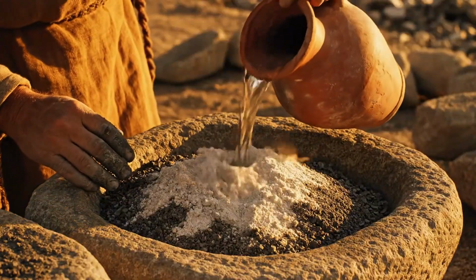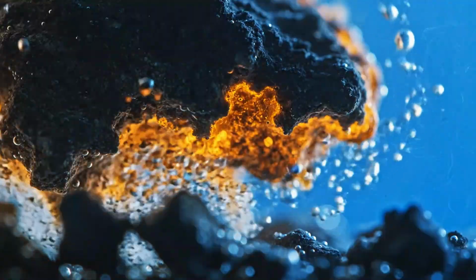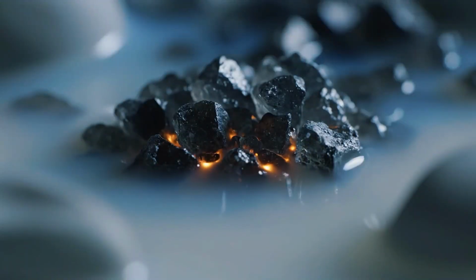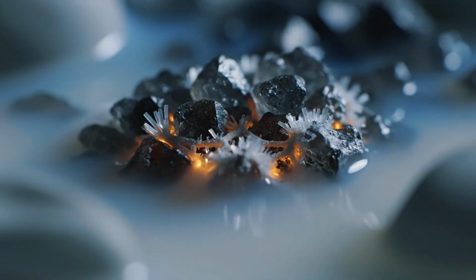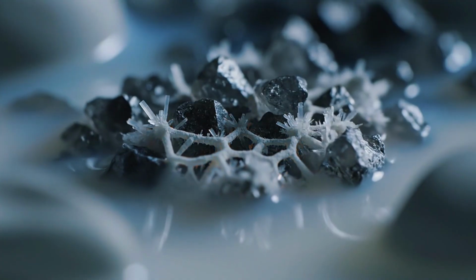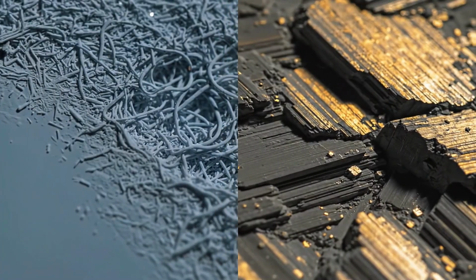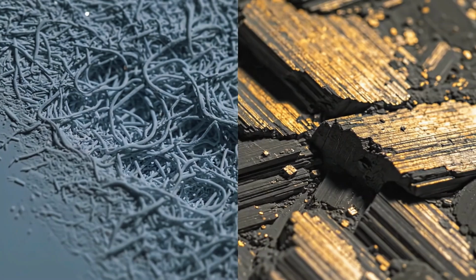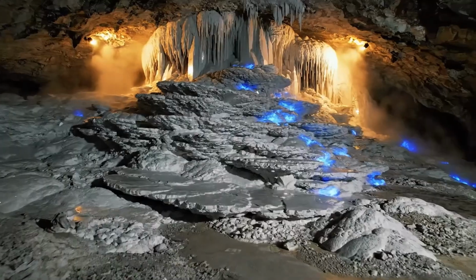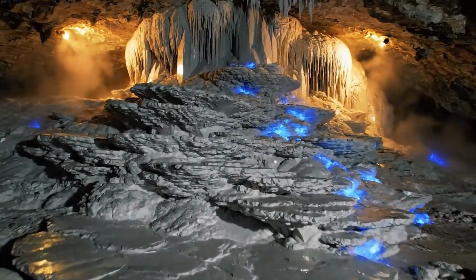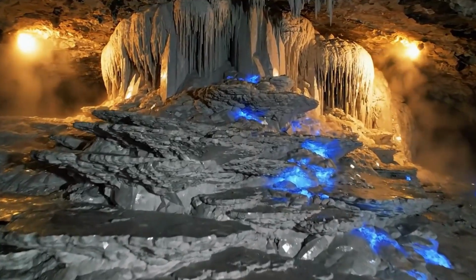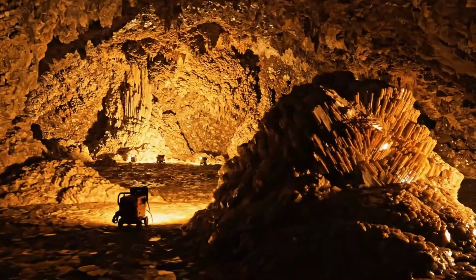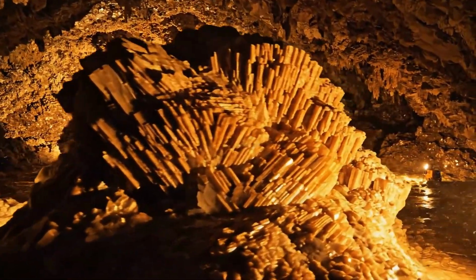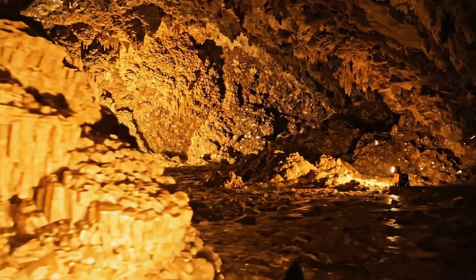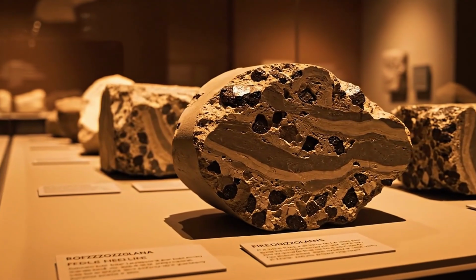When the lime and volcanic ash mix with seawater, a specific chemical reaction occurs. The seawater, which contains dissolved sodium, magnesium, and calcium, reacts with the aluminous and siliceous materials in the volcanic ash. This produces a binding matrix that's fundamentally different from Portland cement. Instead of calcium silicate hydrate, the primary binding phase in Roman concrete is a mineral called aluminous tobermorite. This is a rare, extremely stable calcium silicate mineral that forms at high temperatures in nature, but the Romans managed to create it at ambient seawater temperatures through their specific mixture.